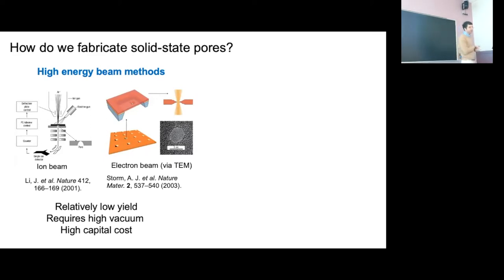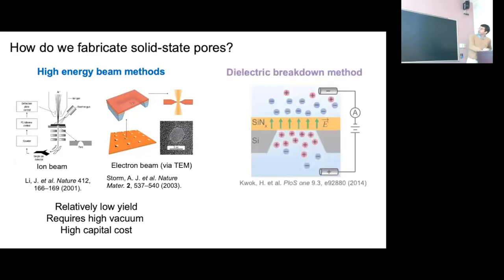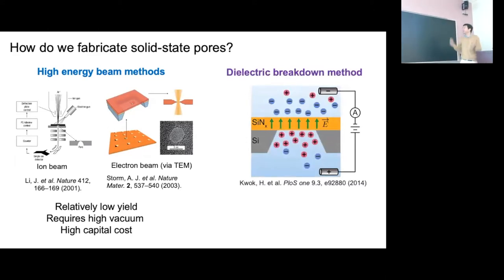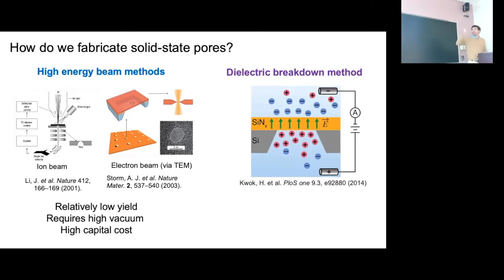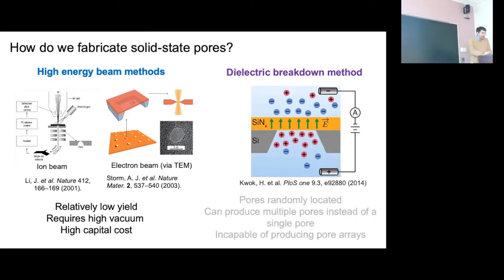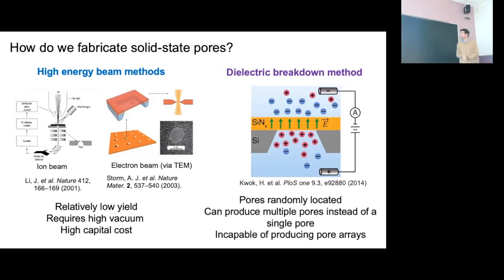For that reason, the Tabard-Cossa group developed a nice method where any group can apply it: take your nitride membrane, stick it in a cell, apply a voltage, and a very high voltage can create a pore via dielectric breakdown. That's a great method because any lab can do it without fancy equipment. However, it has a real drawback: the pores are randomly located, made at some random weak position on the membrane when you blanket-apply a voltage.